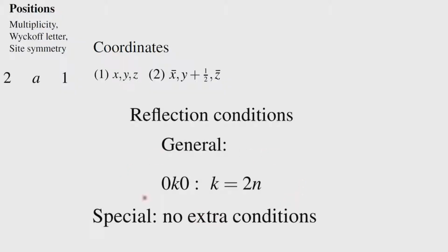So, the 2 double bonds, when they come close to each other, they should come within 4 angstroms, and therefore the unit cell dimension as a consequence will be short. And with this short unit cell, the confidence we can put in the observed systematic absence becomes less, and therefore we can generally see whether this crystal system is either P2 or P21.